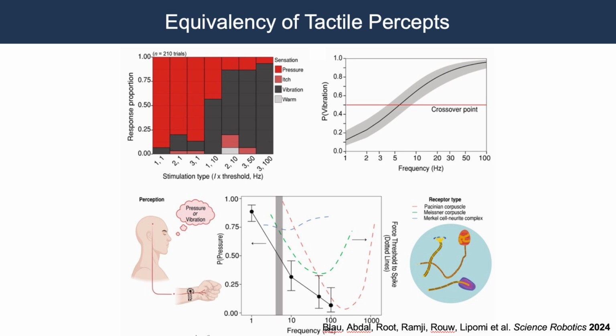So what we did was a combination of the materials innovation, and also a psychological thresholding procedure where we took the smallest noticeable current for each participant and used that as a baseline from which we used multiples of that lowest perceivable stimulation current. So what we have down here is the multiple of the stimulation current, and then this here is the frequency in hertz. And you can see that as you increase the current by a factor of 3, you don't really get a change in percept. But once you increase the frequency from 1 to 10 hertz, you go from predominantly a feeling of pressure to predominantly feelings of vibration.